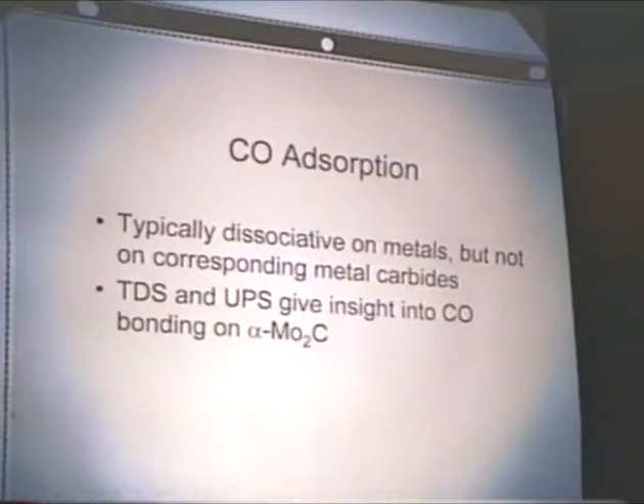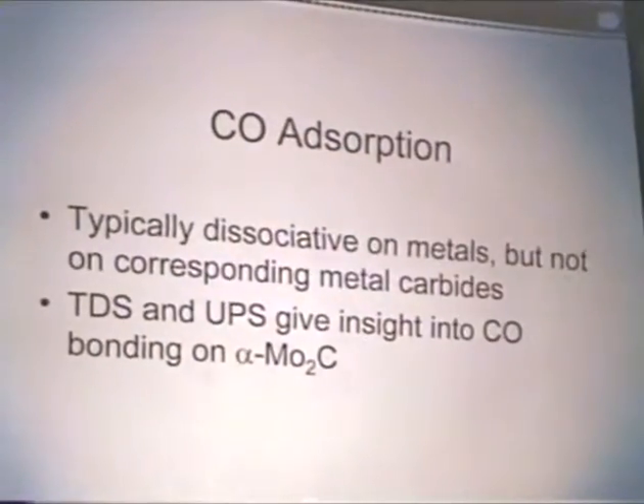Moving on to the second part of our study, which concerns the adsorption of CO on the single crystal surface. CO is typically dissociative on metals, but not on the corresponding metal carbides. And so we plan on investigating that, as well as using TDS and UPS to gain some insight into exactly how CO is bonded to the surface.